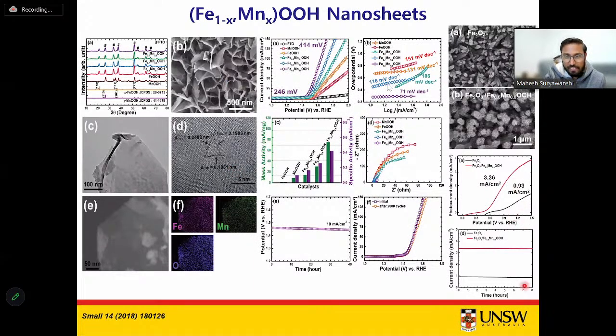However, the interesting point is that if you see the stability, even after 8 hours of a water splitting reaction, you can see barely there is any decrement in the photocurrent density, which demonstrates the importance of having a catalyst on the top of the semiconductor materials for water splitting reaction.